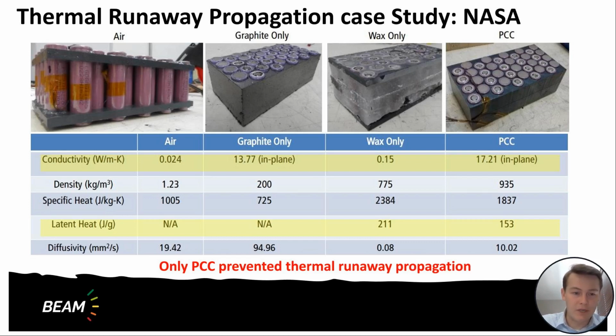So again, the 4S10P with the older model energy cell, but still NMC with high nickel content. We compared a pack with the PCC spacers only, see on the top left there. We also took a pack with compressed graphite. So we took similar density that we use in our PCC, but didn't add the wax material into the matrix, and just ran a test on the graphite.